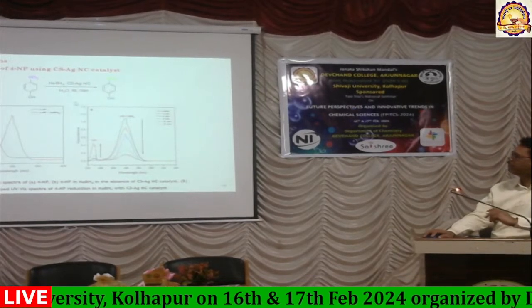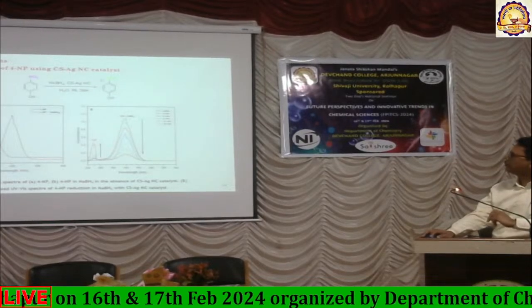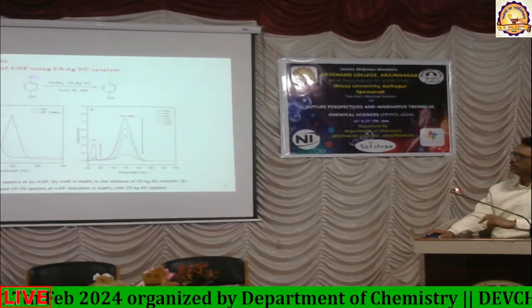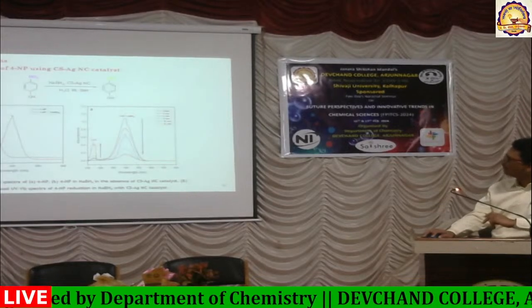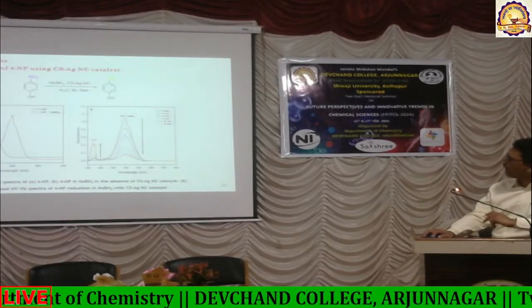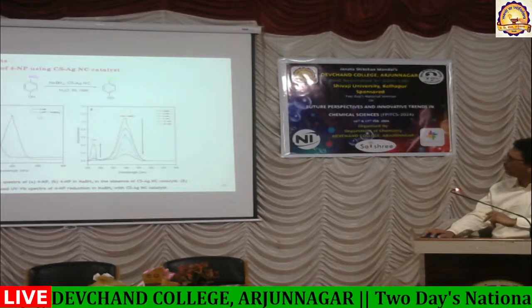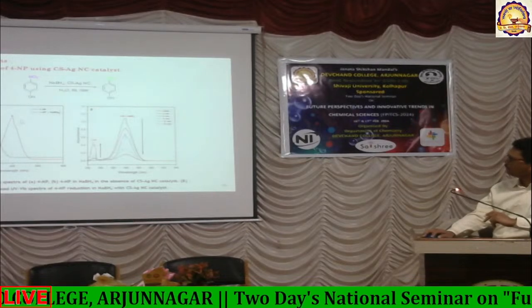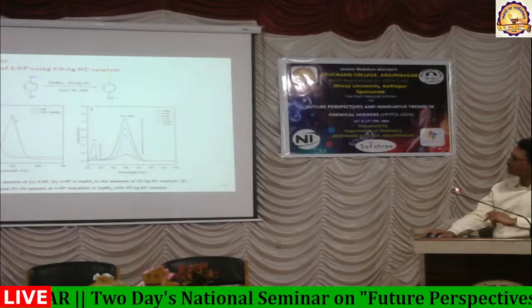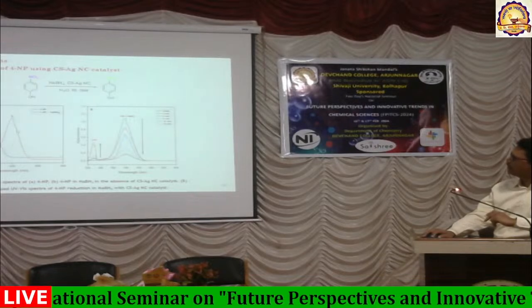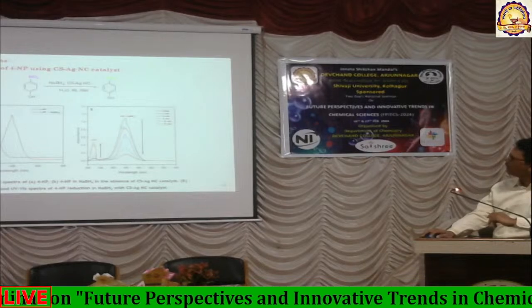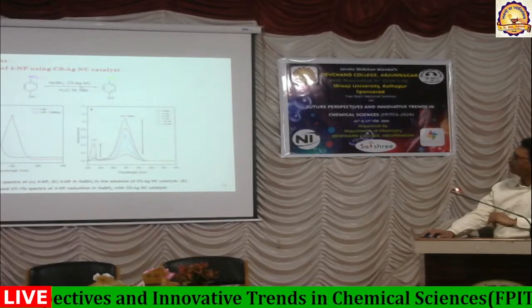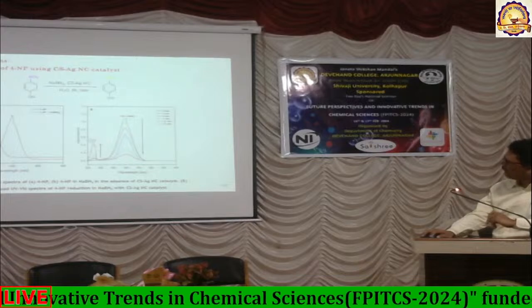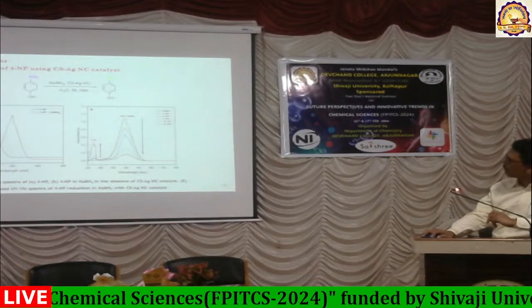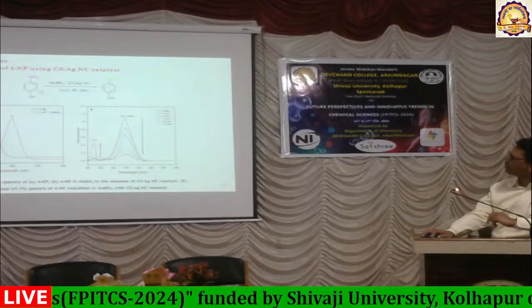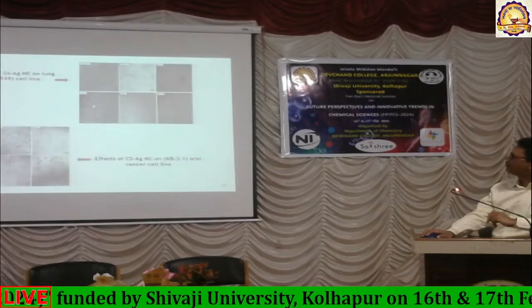This is a chemical property of the chitosan silver nanocomposite, where the nitro group can easily be reduced. So this is an ordinary nitrophenol, and when we add sodium borohydride to 4-nitrophenol, there will be a bathochromic shift, and hence you can see very easily the enhanced UV. And then after some time, when we add sodium borohydride and this chitosan silver nanoparticle, there is another band appearing for 4-aminophenol, indicating the conversion of nitrophenol into aminophenol.